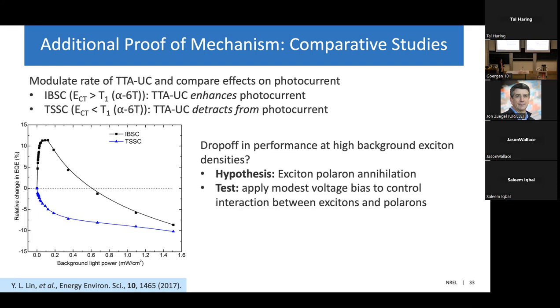But we did have the question of why there was this drop-off in performance for the intermediate band solar cell as we moved to higher background light intensities. And our hypothesis was that the device was now suffering from exciton polaron annihilation. So as you flood the system with extra light, you're also producing a lot more polarons that can now interact with the excitons that are being probed and annihilate.